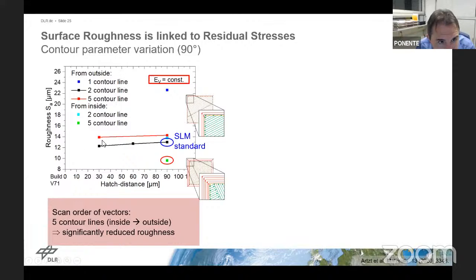It's a little bit of a complicated diagram, I apologize. At the bottom, you see the hatch distance, and on the left-hand side, the surface quality in terms of Sa again, the arithmetic mean surface roughness. And I want to point out particular points. This is in blue, highlighted here, the SLM standard parameter that I've been using in the past, which gives you, depending on the sample side, a surface roughness on the order of 12 microns. And by optimizing the number of contour lines and the contour parameters, we were able to reduce that quite a bit. I put an error bar on this because sample positioning on the base plate and reproduction leads to changes here. So I wouldn't be too specific about the exact value, but there is a trend that we can improve that by changing the scan strategies that the manufacturers provide. So that's actually an important thing.